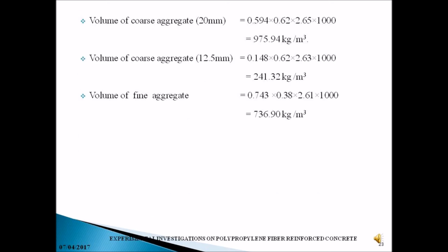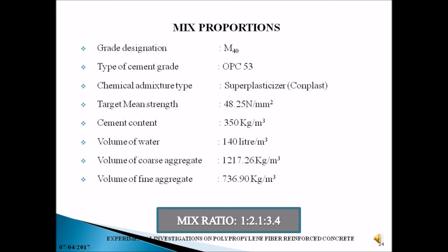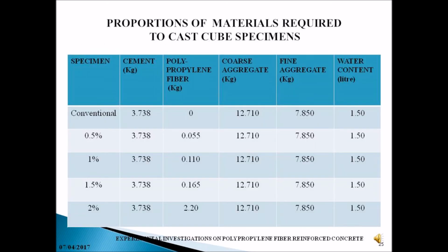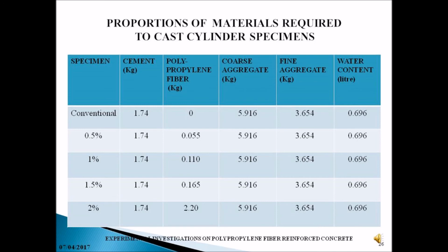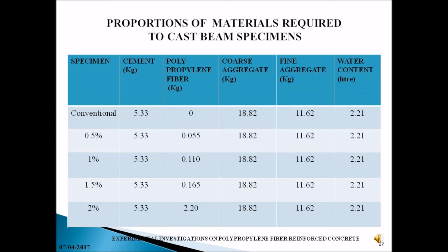Two types of coarse aggregate have been used, 20 mm and 12.5 mm, in order to fill the pores inside the concrete mixture. And finally the mix proportion. The mix ratio has been achieved as 1:2.1:3.4. These are the proportions of materials required to cast the cube specimens. These are the proportions of materials required to cast the cylinder specimens. These are the proportions required to cast the beam specimens.